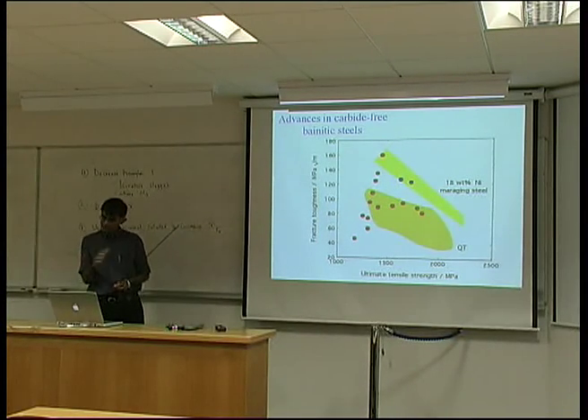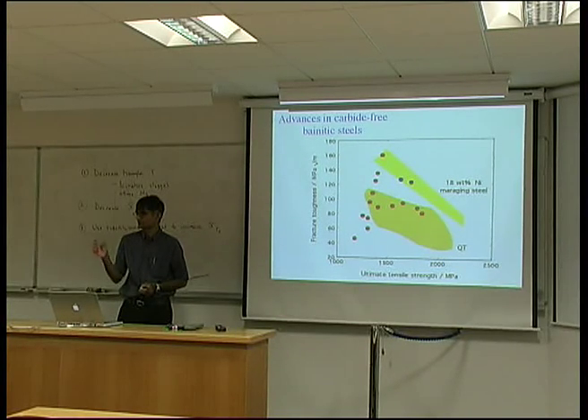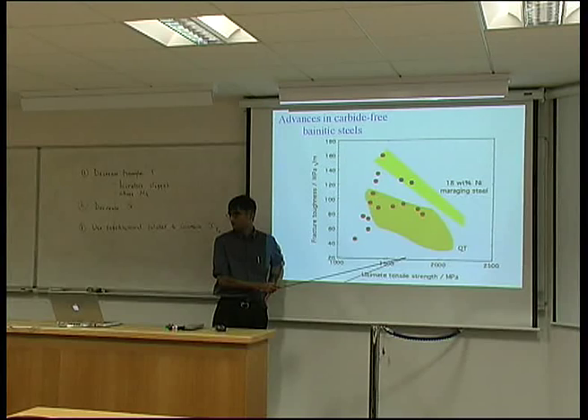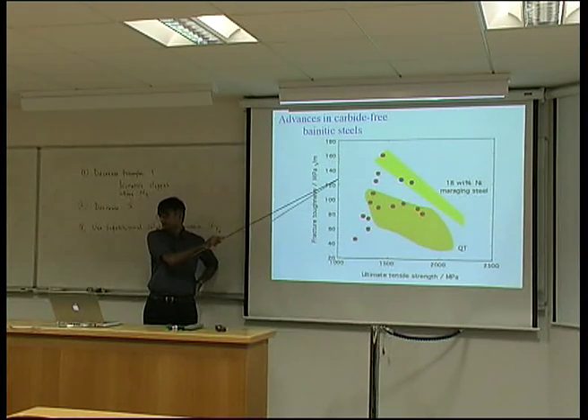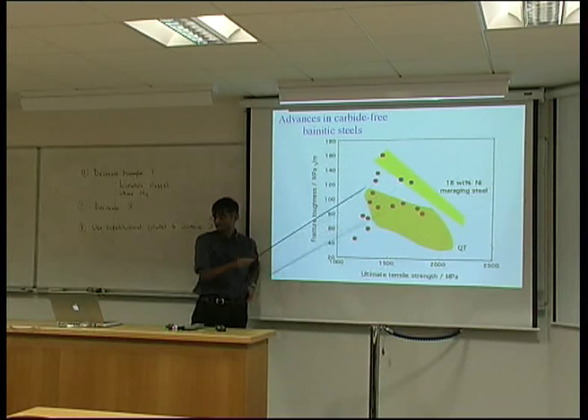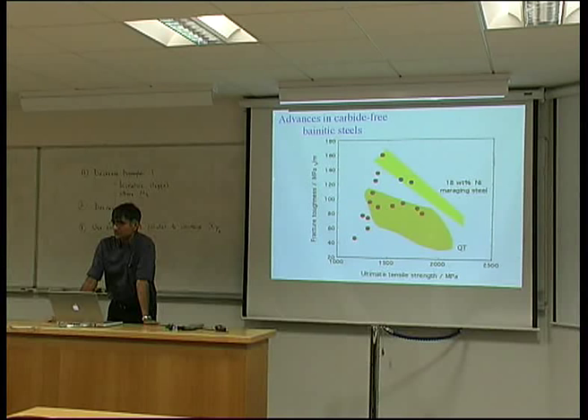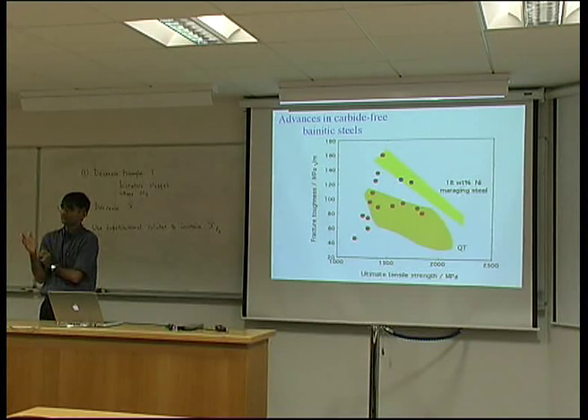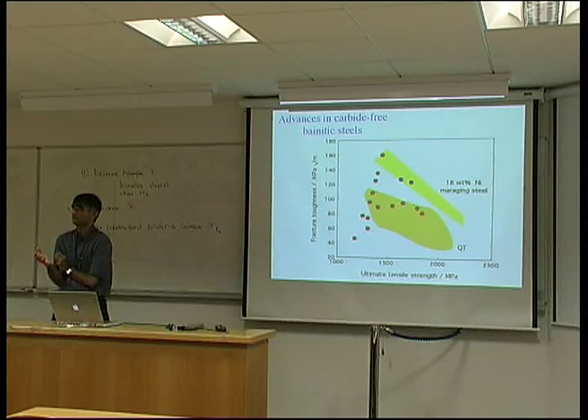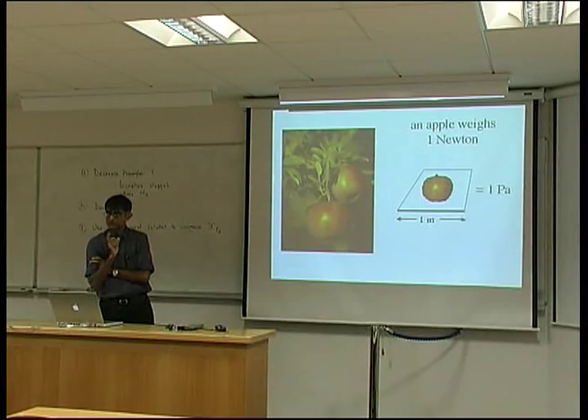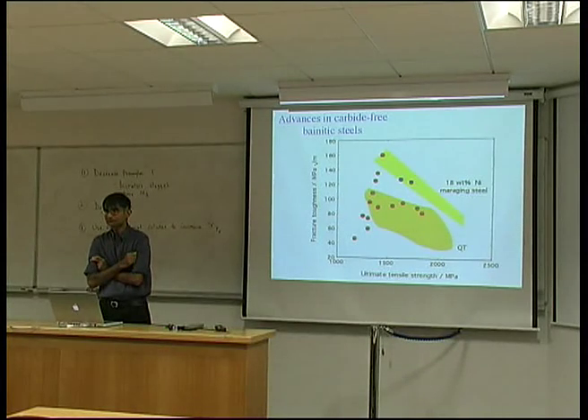This material is actually being used on real trains carrying 300 tons of molten steel, designed using the theory we've learned. You can control the strength of these steels by altering the transformation temperature and thus the size of the bainite plates. Another set of steels designed using the same theory achieves a strength of about 1600 MPa and a fracture toughness of about 130 MPa√m — the same as maraging steels, which are 90 times more expensive.